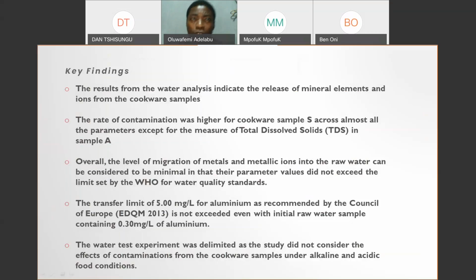So overall, the level of migration of metals and metallic ions into the raw water can be considered minimal, in that their parameter values did not exceed the limit set by the WHO for water quality standard. For instance, the transfer limit of 5.0 milligrams per liter for aluminum, as recommended by the Council of Europe 2013, is not exceeded even with the initial raw sample containing 0.3 milligrams per liter of aluminum. So the water test experiment was delimited, as the study did not consider acidic food condition.